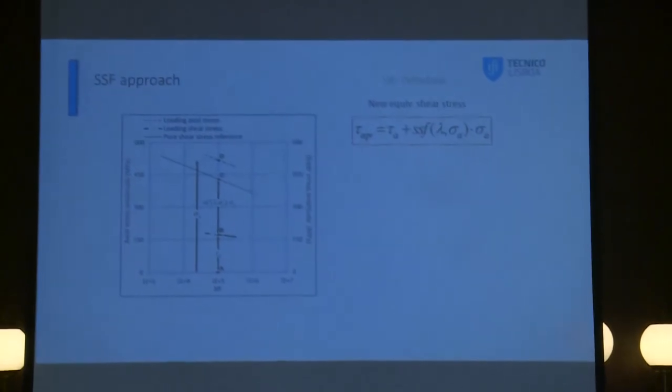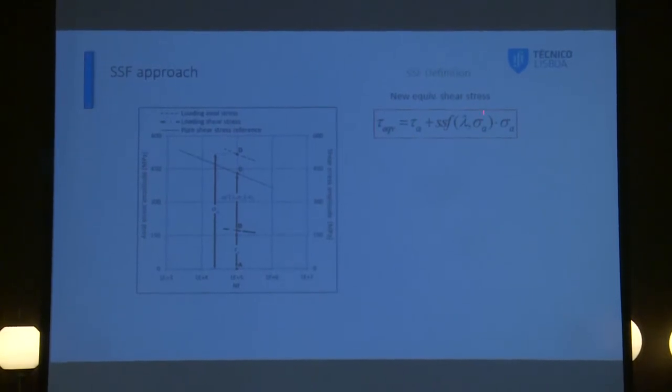Let me move now to our approach. As we are dealing with multi-axial fatigue, I'm not sure if you are familiar with this, but we can separate the biaxial or multi-axial loading in several components. In this case, our proposal, the SSF definition is based on separating the shear stresses, based on the amplitude of the shear stresses, plus a coefficient that takes into account the amplitude of the normal, of the axial stresses. We can separate the shear and normal axial stresses. Let me just illustrate this for a better understanding.